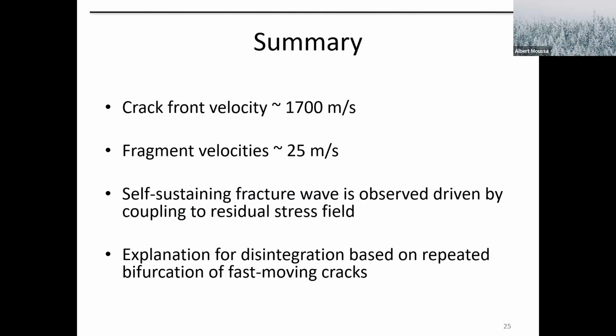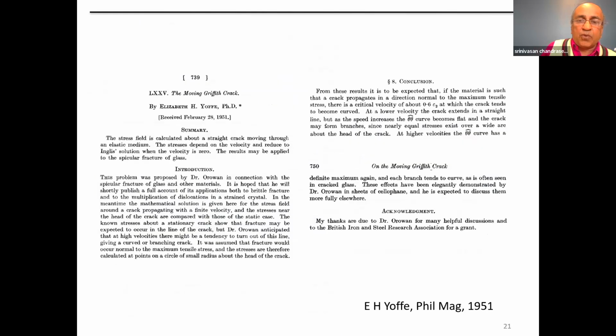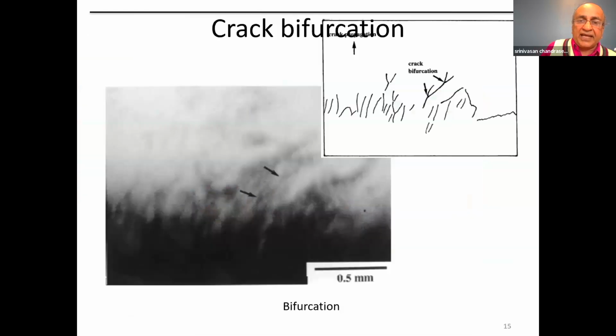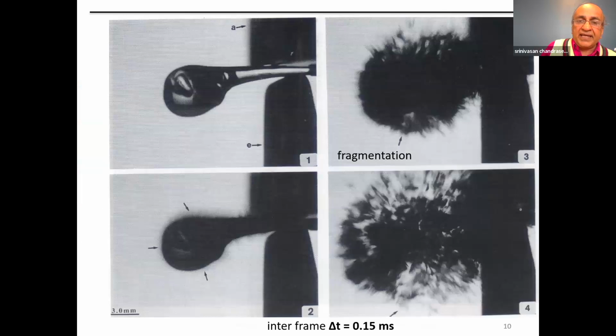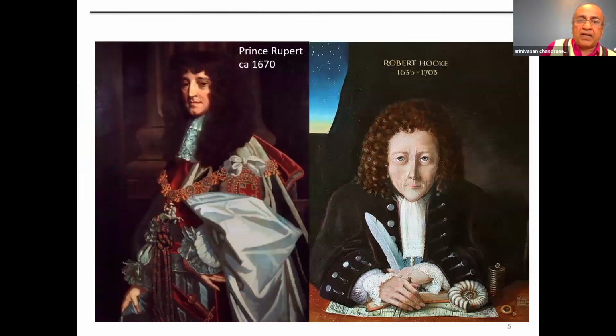Okay, so that's what's happening inside. What about in the surface? At the surface, it runs into the compression zone, and the crack decelerates. It almost comes to a stop by the time it hits the surface. But the surface breaks down because you had essentially expansion inside and it's just pushing it out? Well, actually, for seeing what happens at the surface, it's better to look at the picture from the glass...